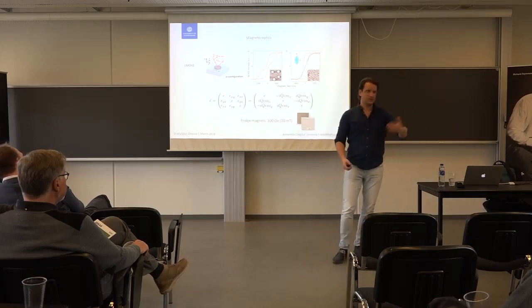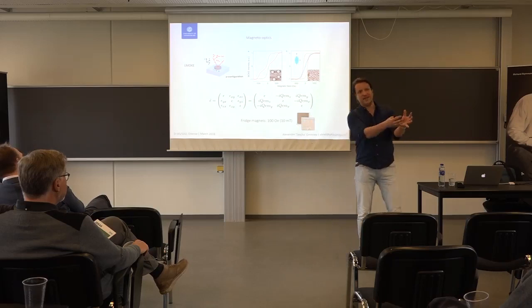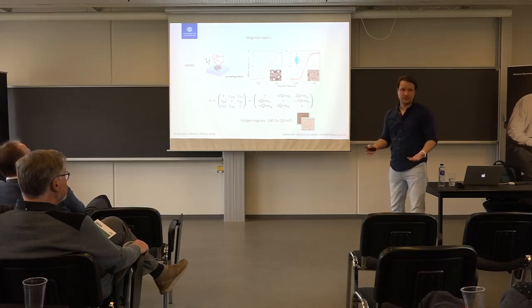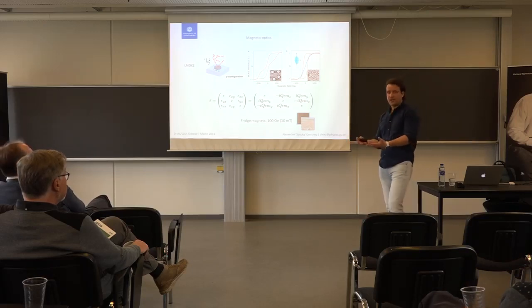You magnetize something, you remove that magnet, and the information stays there. So that is the nice way to store your information: you magnetize something along the so-called easy magnetization axis. Whereas along the hard axis, there is no width to that loop, so you do not maintain the written information.